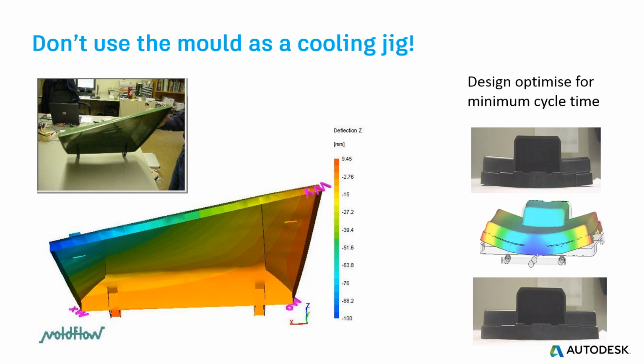So this twisted bin lid was kept in the mould for an extra 40 seconds to help keep it flat. So it's running over cycle time. They're making more bins and lids. It was center gated, and Moldflow showed that had it been end gated, it would be nice and flat.